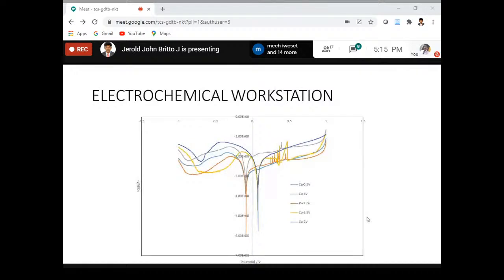This graph is between potential and log of I by A, that is current versus area. Based upon this, I have done this electrochemical corrosion test for all five different samples. From this, I have found that when 2% vanadium is added with copper, it has greater corrosion resistance when compared with the other compositions.